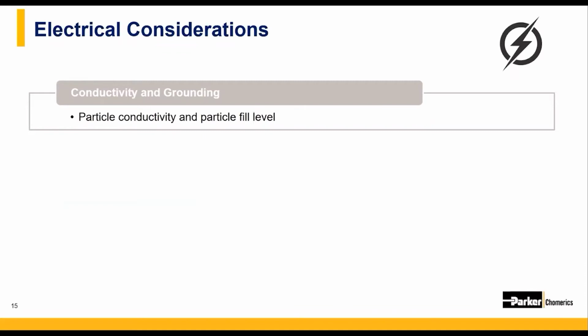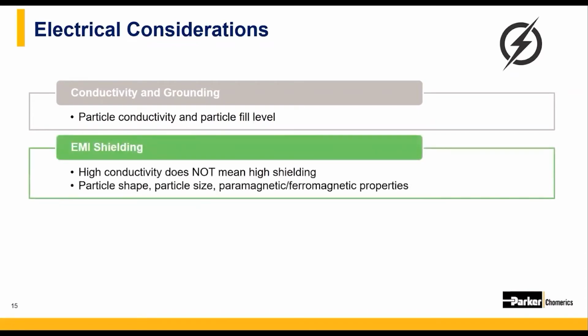So coatings need that even distribution of the fillers throughout the part to make sure the entire surface has the ideal properties. On a very important note is that EMI shielding is not always directly correlated with particle conductivity. Let me emphasize this. High conductivity particles will provide good EMI shielding, but low conductivity particles can also provide very good EMI shielding because of factors such as particle shape, particle size, and paramagnetic or ferromagnetic properties. These properties will actually impact the shielding at lower ends of the frequency spectrum, specifically in the magnetic field range.